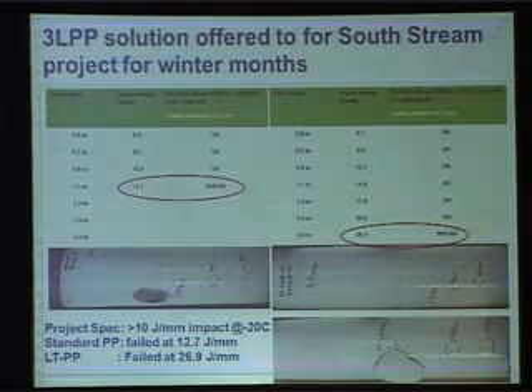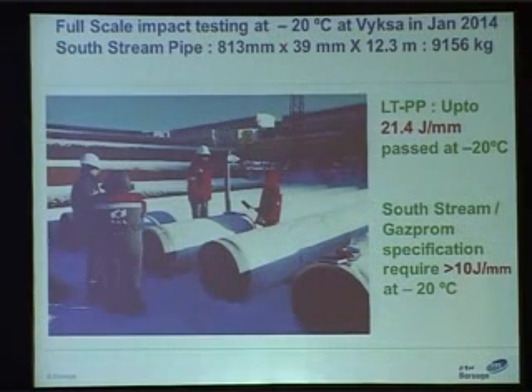Now, what we found in laboratory testing is that the standard PP withstands 10 joule per millimeter, but cracks around 11 to 13 joule per millimeter. As against this, low temperature polypropylene could withstand up to 26.9 joule per millimeter at minus 20 degrees centigrade. In field testing at minus 20 degrees centigrade at the coating company Vixa Steel in Russia, low temperature PP could withstand impact up to 21.4 joule per millimeter.